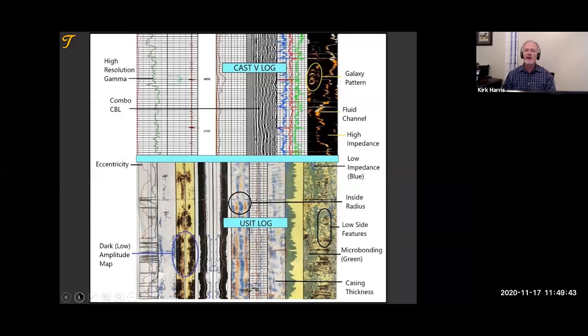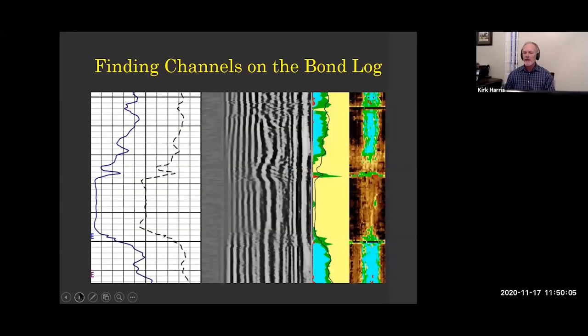And with the ultrasonic log, we see galaxy patterns as shown up above that tell us when the formation is very close to the casing. We can see clearly, this is about a 1 to 2 inch wide channel flowing up. You see some great things with the ultrasonic log. Finding channels is why we run that ultrasonic log on the right.